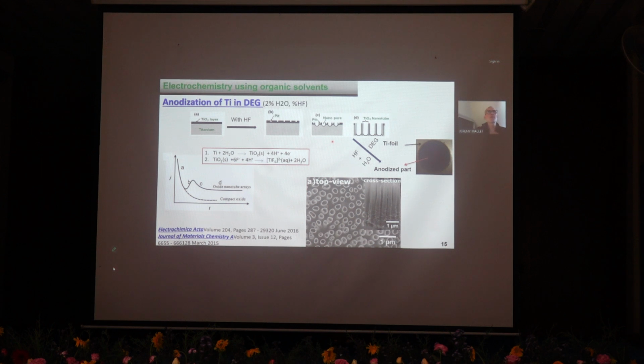So here we mainly work in diethylene glycol with some content of water and HF. So it's a two-step process. First you create titanium dioxide, and then we have a chemical dissolution of this oxide to create the pores. By adjusting the parameters, you can go from a porous membrane to structuration to get some nice nanotubes like that. So here is the titanium foil. After anodization, we have the titanium dioxide.